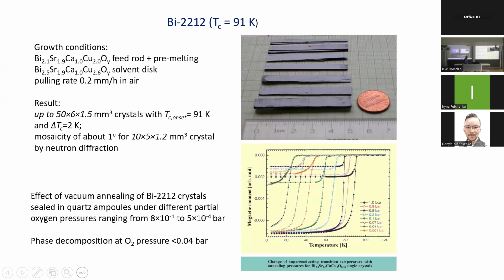Bismuth 2212. It's the most well-studied system. So again, you have to prepare such a rod, remelt it. The best and the thickest crystals are grown using a separately prepared solvent disc, but the key parameter for the successful growth is the pulling rate. It's quite low, 0.2 millimeters per hour. And only in this case, we are able to prepare such large and thick bismuth 2212 crystals. If we increase the pulling rate, the thickness is below 0.2 millimeter along the C-axis, and the dimensions in the AB plane are also reduced.